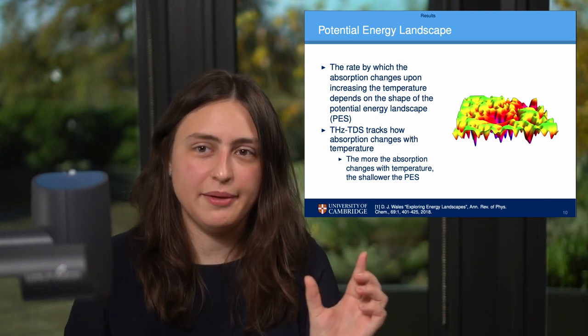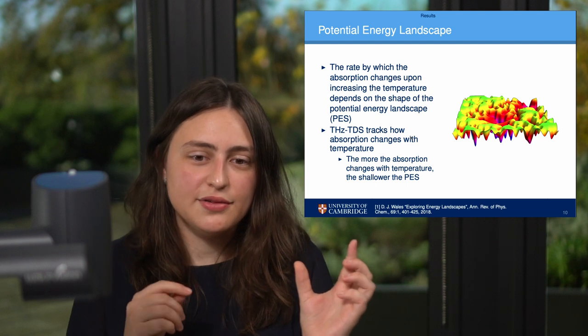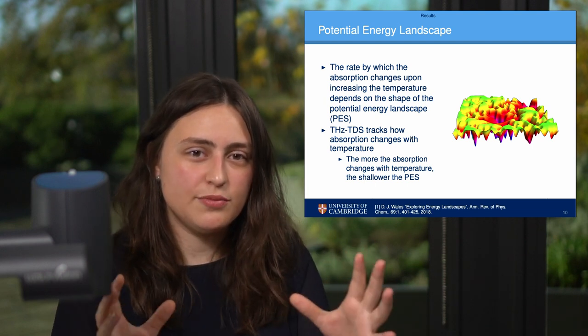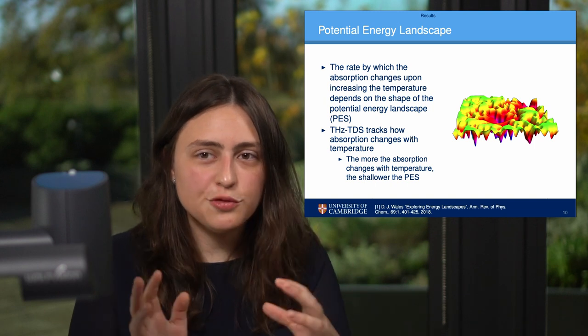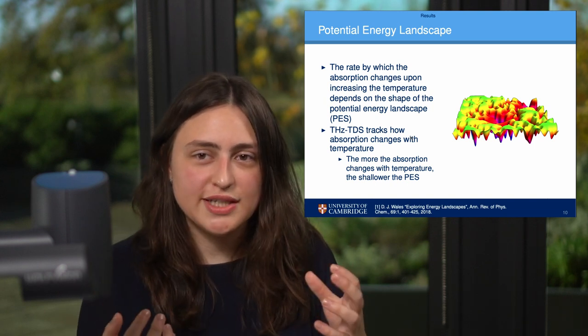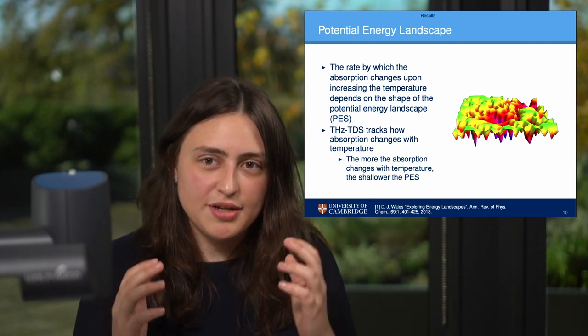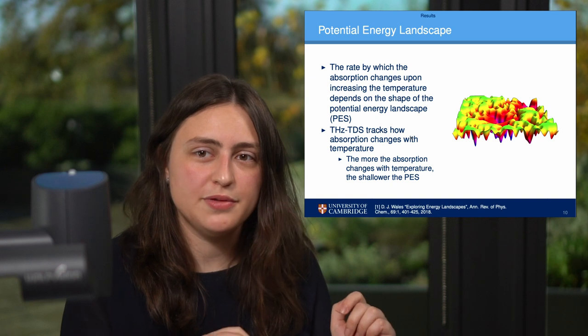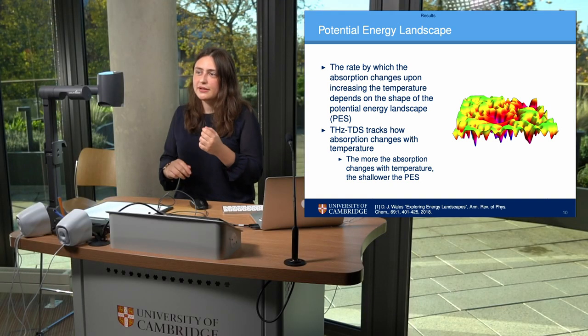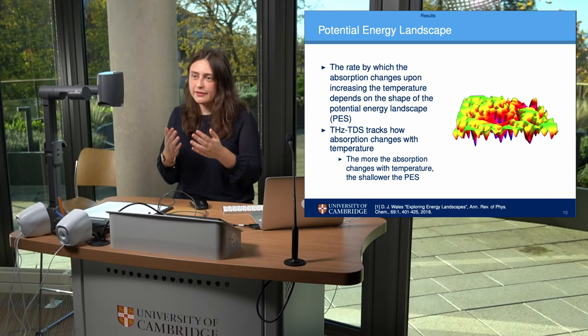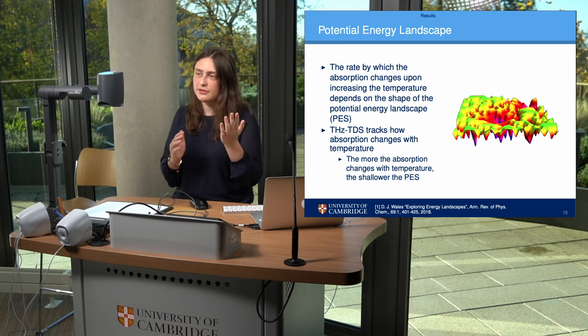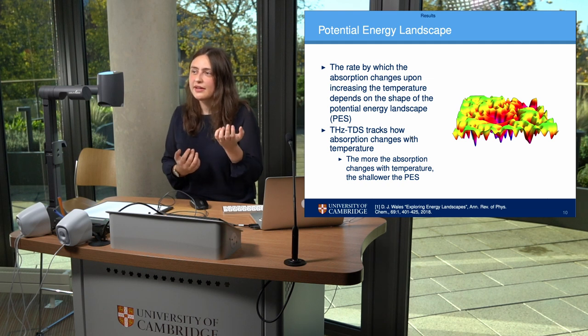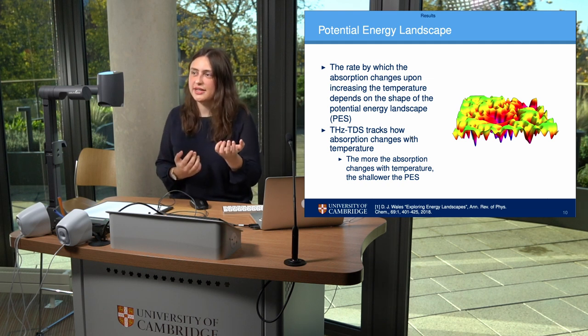If that happens, your sample has more potential conformations — it can access more conformational states, it can move more, and by moving more, the dipole moment changes more. We are measuring with terahertz spectroscopy the change of the dipole moment. By varying the temperature and measuring sample absorption, we can track the shape of the potential energy landscape.